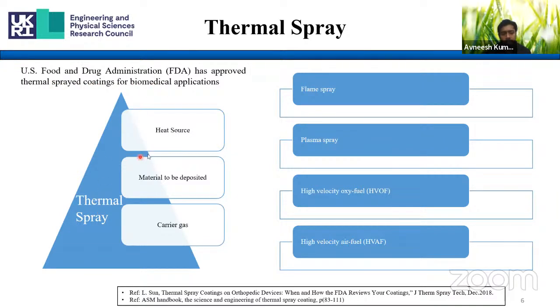And in thermal spray, as we know, basically it contains three parts. One is the material that we want to deposit. Another is a heat source, which is required to melt or semi-melt this deposited particle. And then there is a carrier gas, which propels this molten or semi-molten particle onto the substrate in order to form coatings. Based on this principle, a number of coating technologies have been put forward, including flame spray, plasma spray, high velocity oxy fuel, high velocity air fuel, and detonation gun.